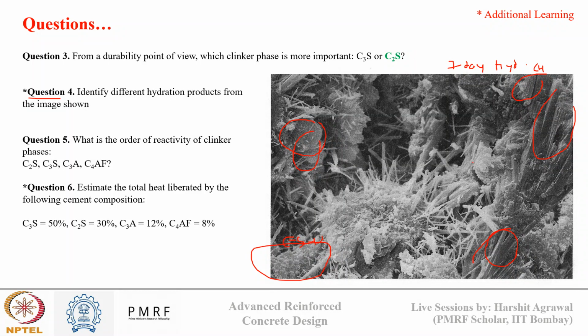I won't go deep into the structure of cement hydration because this is beyond the limit of this course, but this was just an explanation of how from an SEM image we generally identify where the different products are formed. CH has a hexagonal crystalline structure, CSH has a gel-like structure, the needle-like structure is ettringite, and the plate-like geometry is monosulfate. In this way, we can distinguish different hydration products that are formed in cement hydration.